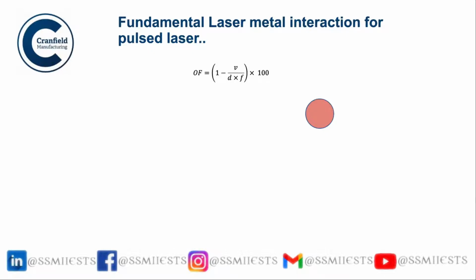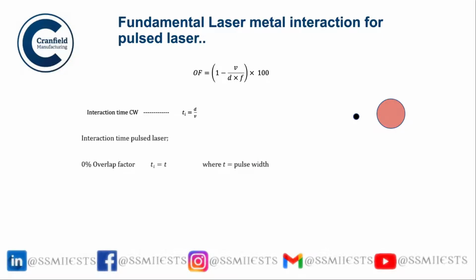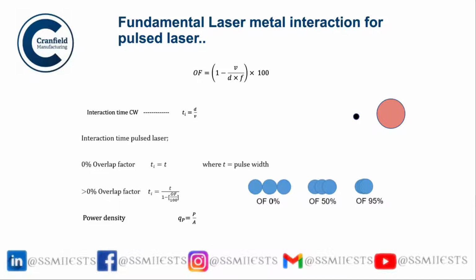Now I will talk a little bit about pulse laser. I would like to show that this is the interaction time which an infinitesimal spot experiences when the spot passes over, but here it is not continuous. Here it is applied with a particular frequency per second, and therefore the interaction time depends not only on the size of the beam and the velocity, but also on the frequency. This is the formula for converting frequency with overlap factor. Here I tried to show how different overlap factors can be built into the interaction time calculations, and that helps in getting a proper understanding of how much heat is actually applied in a particular situation.